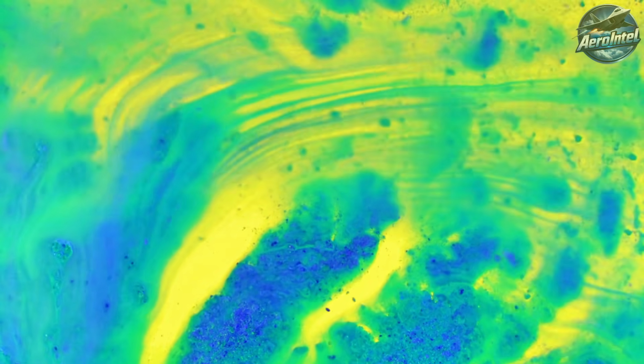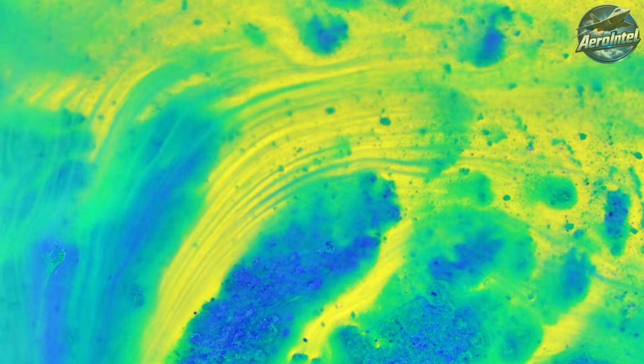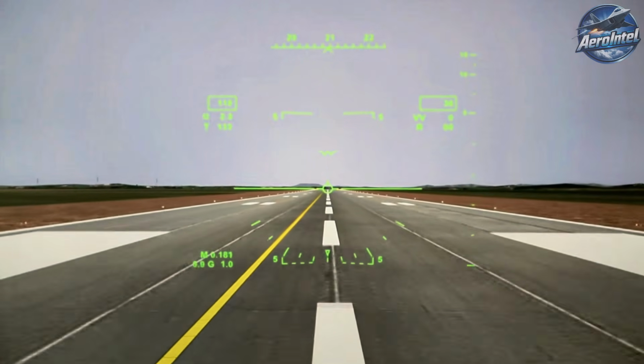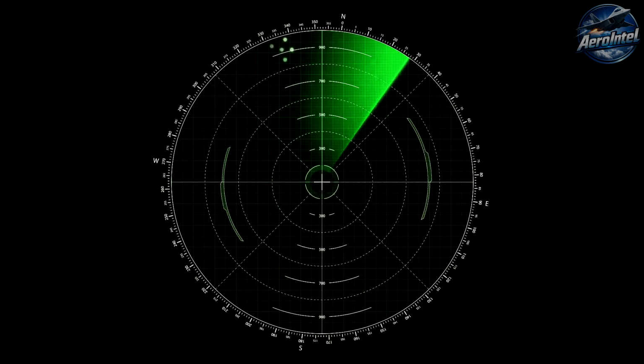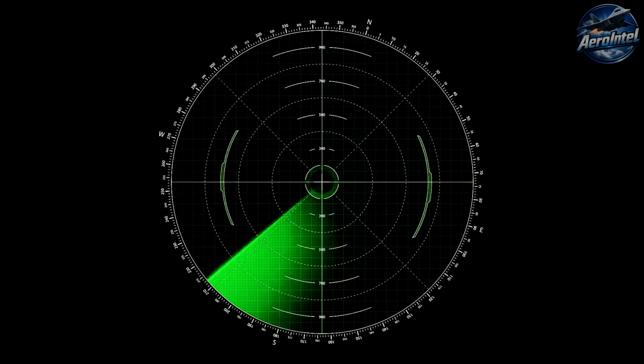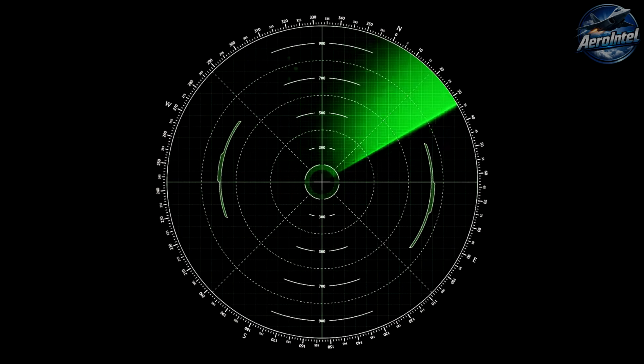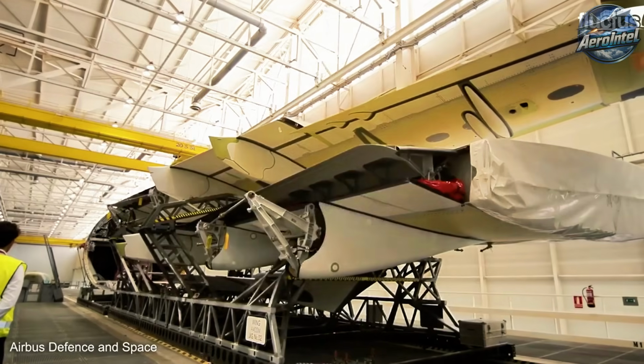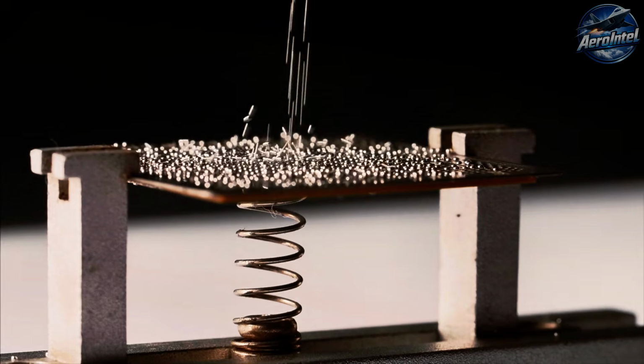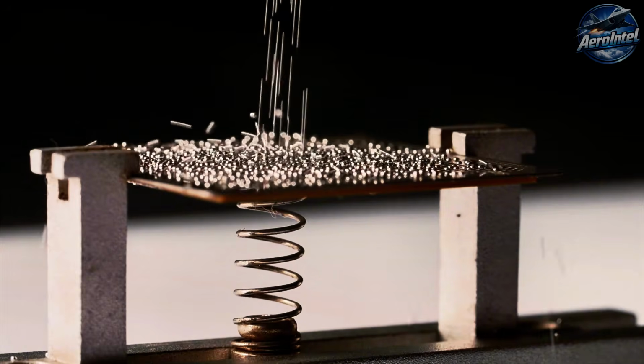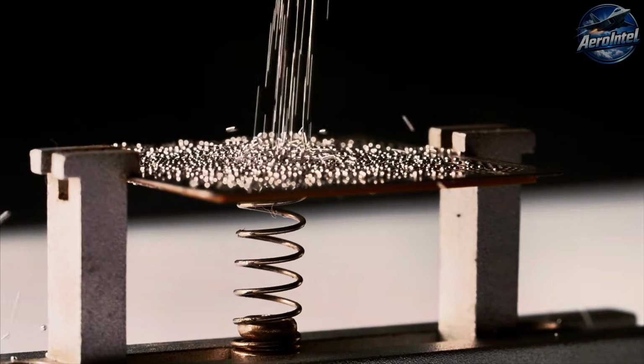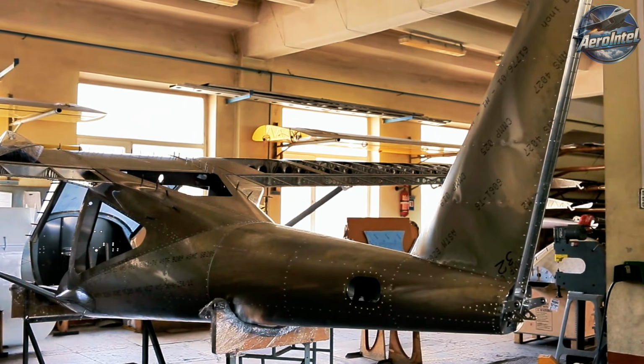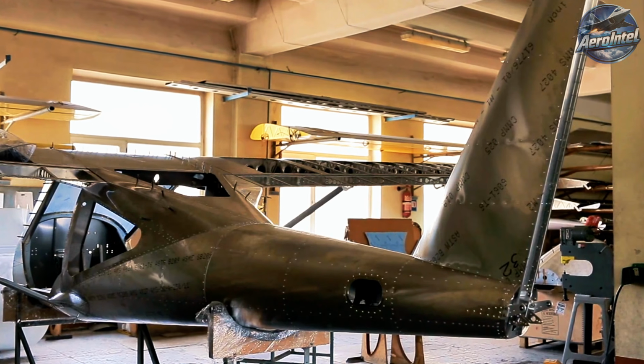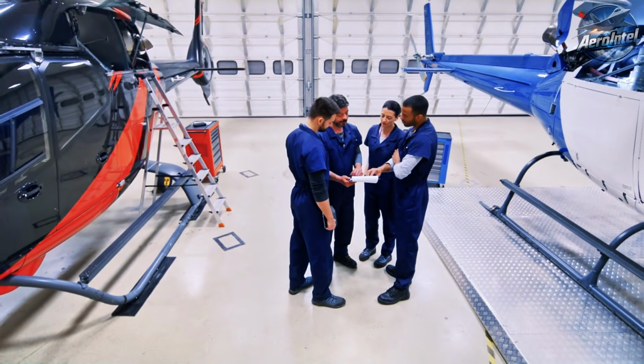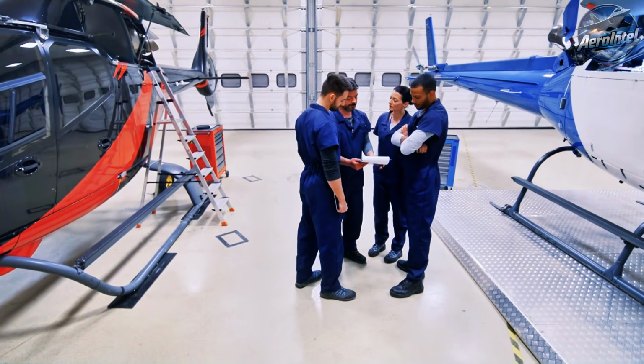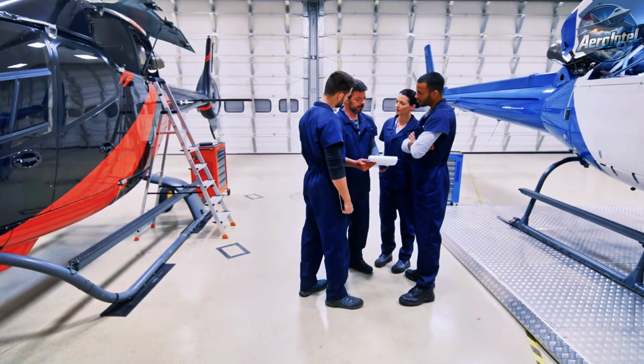Welding, ironically, creates its own radar problems in this context. Weld seams are not perfectly flat. The heat-affected zone can create subtle surface deformations, ripples, and steps that disturb the airflow and create localized radar returns. In the context of stealth engineering, where designers are trying to reduce radar cross-section by orders of magnitude, a precisely installed flush countersunk rivet is actually a better solution from an electromagnetic standpoint than a weld bead.